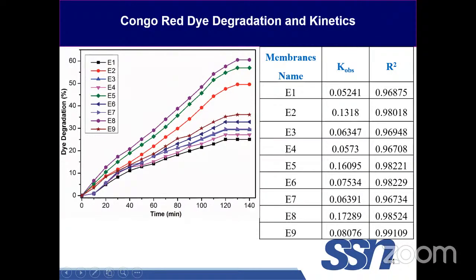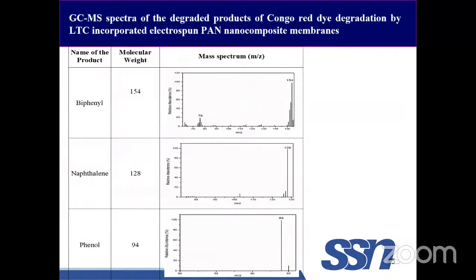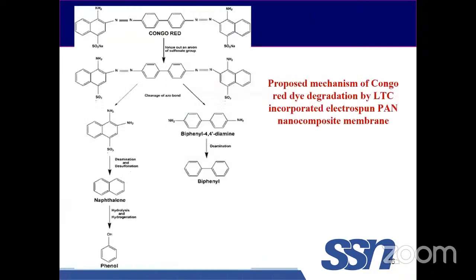So in order to identify what is the degraded product of the dye, we took GCMS of the samples. So we found the byproducts as biphenyl. The Congo Red has been converted to biphenyl, naphthalene, and phenol. So this is the corresponding GCMS spectra. From this GCMS result, we derived this equation.